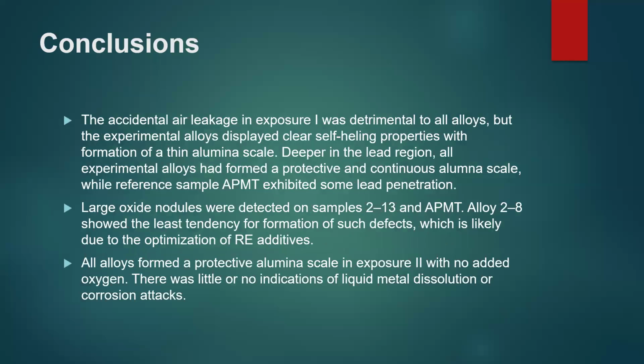Third, the accidental air leakage in test condition 1 was detrimental to all alloys, but the experimental alloys displayed clear self-healing properties with formation of thin alumina scale.